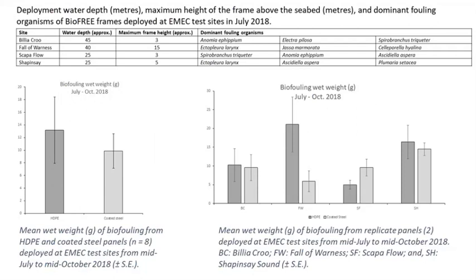Again, this is only indicative data because it's quite early on in the studies, but the fouling is correlated with the tidal speed. So the highest tidal speed has the highest amount of fouling, and in fact it goes proportionally down based upon the current speeds. We're also seeing that the greatest difference between HDPE and coated is in that highest tidal site, so suggesting that the coated panels may be offering some protection from fouling in higher tidal velocities.